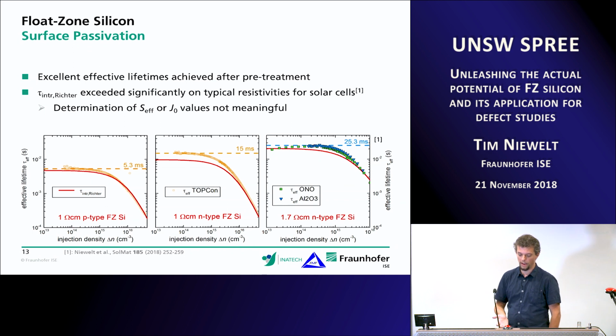That means that on such materials, on these materials that most people are working on and most people are reporting, for example, surface recombination velocities on, it's not meaningful to do that at the moment with the Richter model, because basically, if we would do that for the TOPCon passivation here, or for the ONO and aluminum oxide on these samples, we would end up with negative surface recombination, which would be great to have, but it's just not physically meaningful. So at the moment, I would say that just using the Richter model to extract your surface recombination is a wrong thing to do. If you are really interested in the surface recombination velocity of a surface or of a passivation scheme, then you really have to go all the way and do a thickness variation.